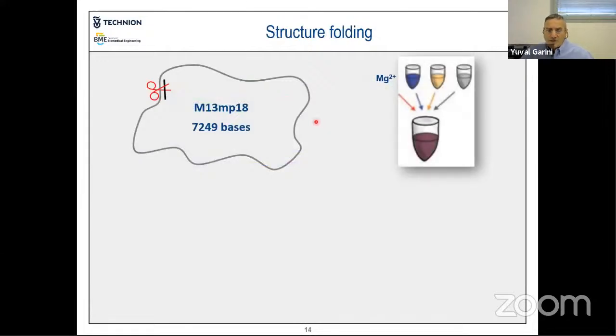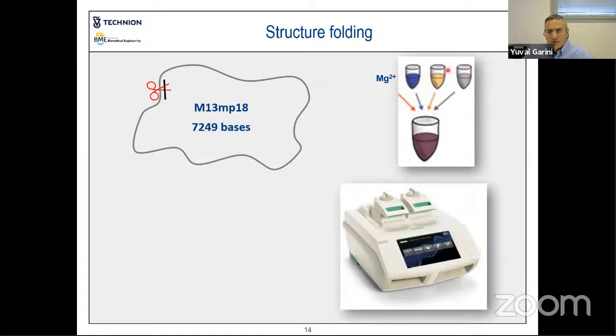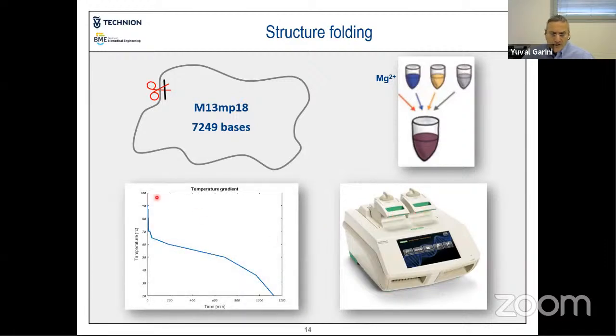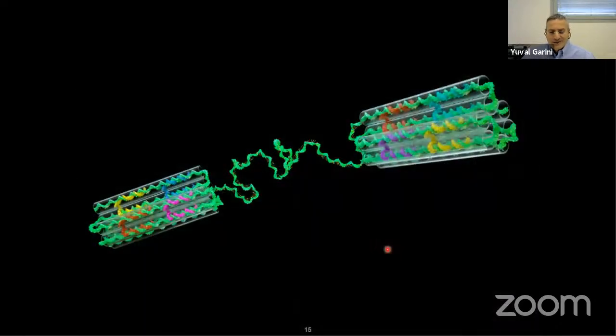The procedure of structuring, once you have the actual plasmid and what are called the staples, a very long list of short single-stranded DNA pieces, is not very complex. You mix everything together with the right salt concentration and pH level, and you run a PCR temperature cycle that basically starts from a high temperature and slowly goes down based on different parameters that I will not enter into in fine detail. And if everything works well, you get your structure at the end.